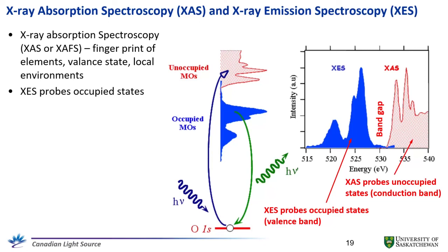If you increase the energy enough that you excite the low-level electrons into an unoccupied band, during this process you measure the transmission or fluorescence from the sample. If you reach this band and the electron is excited, the absorption, your measured signal, increases dramatically. So you measure this intensity versus energy, and here you get the X-ray absorption.